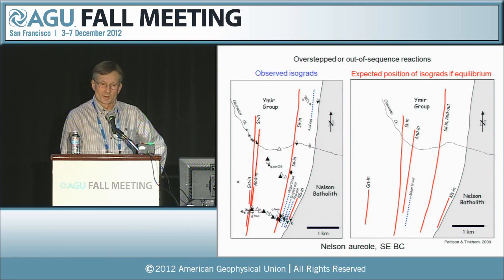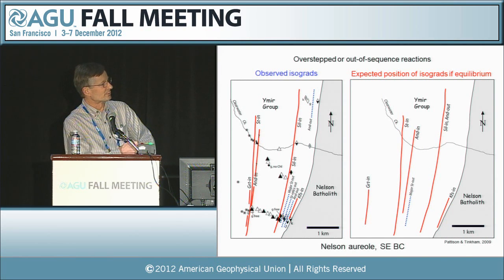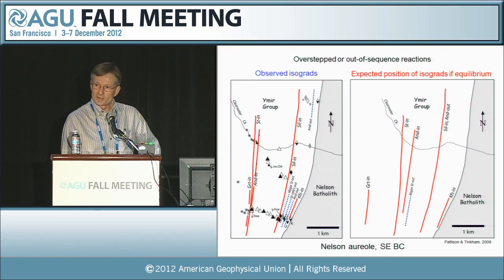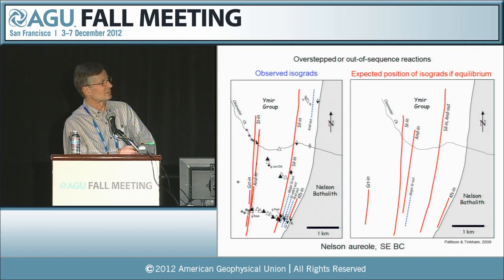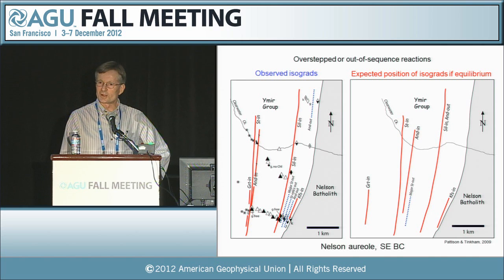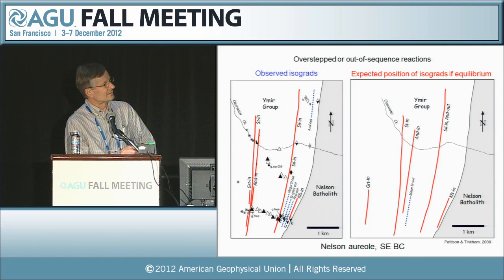A comparable example comes from the Nelson contact aureole in British Columbia. This map on the left shows the distribution of mineral assemblages and isograds based on those. If you take the average composition of the pelites in the contact aureole and calculate an equilibrium phase diagram for it and ally that with a thermal model, one can predict the sequence and spacing of the isograds. And that's what is shown on the right-hand map. And you can see that there are some differences between the two.